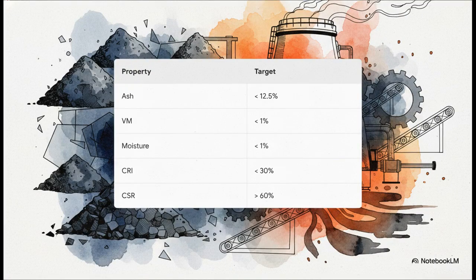This right here is our ultimate optimization blueprint, keeping moisture under 1%, volatile matter under 1%, CRI below 30%, and CSR above 60%. When we hit these exact marks using smartly blended domestic and imported coals, we guarantee lower fuel rates, far fewer bottlenecks, and we absolutely skyrocket our blast furnace productivity.